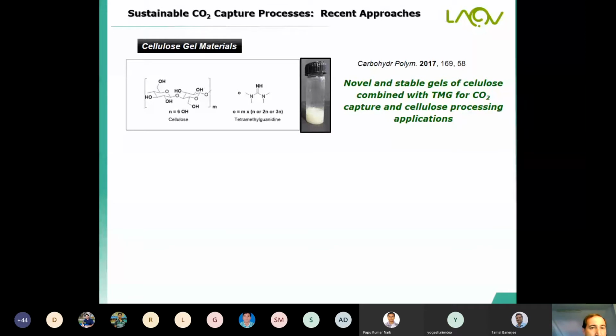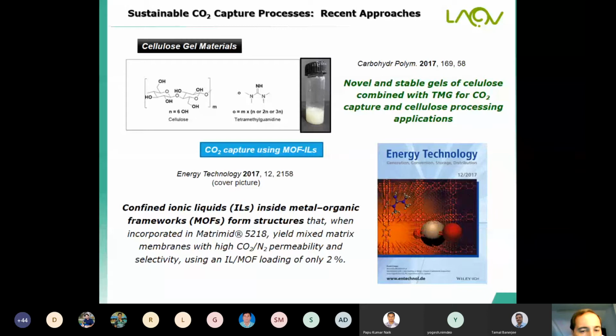But in this context of the sustainable CO2 capture process, we already checked other approaches, like using metal organic frameworks, the MOFs, in combination with ionic liquids. And this kind of combination is interesting because it's possible to incorporate in membranes, in particular in this Matrimid membrane, and form a mixed matrix membrane. And this is very interesting for the CO2 nitrogen permeability and selectivity. It's possible to separate CO2 from nitrogen very well.